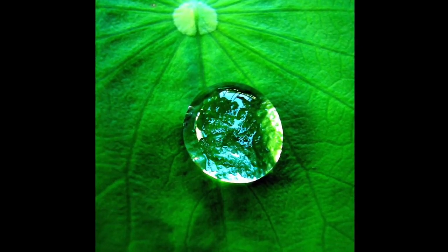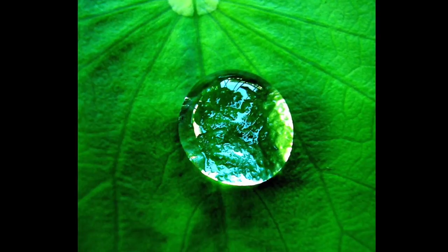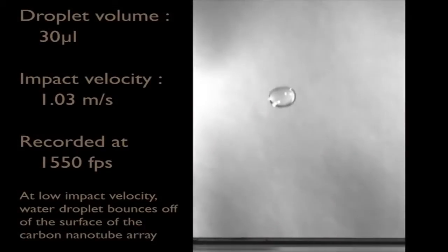Carbon nanotube sponges are hydrophobic and oleophilic by nature with a contact angle at approximately 160 degrees for water droplets. Since the nanotubes are made up of sheets of graphene, most of the bonds are between carbon atoms, which all have the same electronegativity.